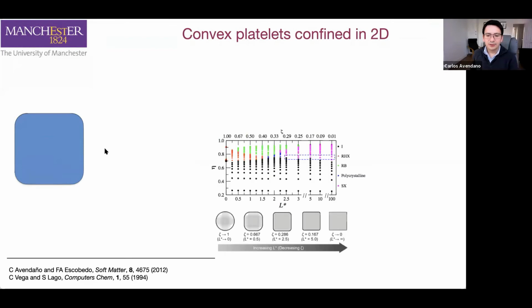So what we decided to do is to put four of them together. And by just changing the aspect ratio, we can map between the perfect disk and a perfect square. The void in the middle is not relevant for two-dimensional systems because the neighboring particles are not going to see that hole in the middle. So we can avoid having to deal with that.